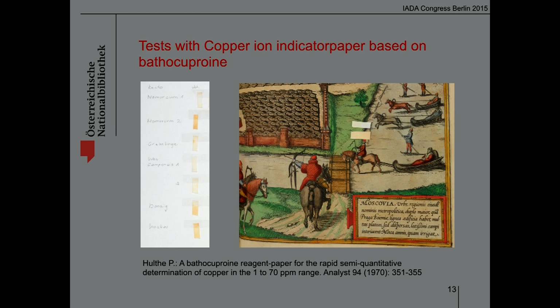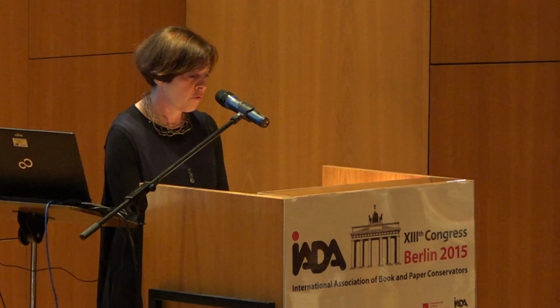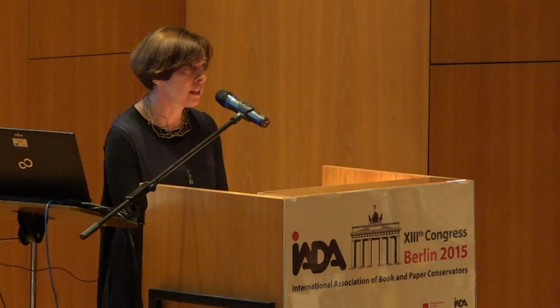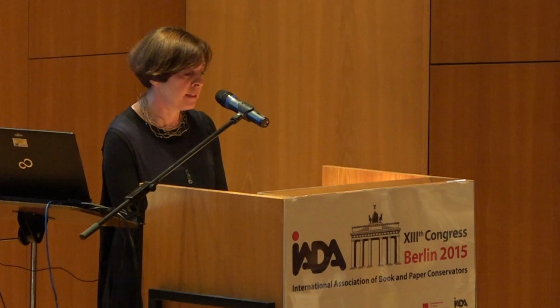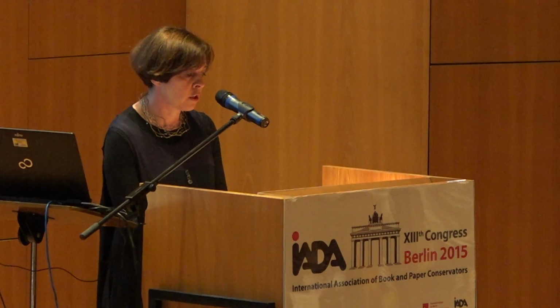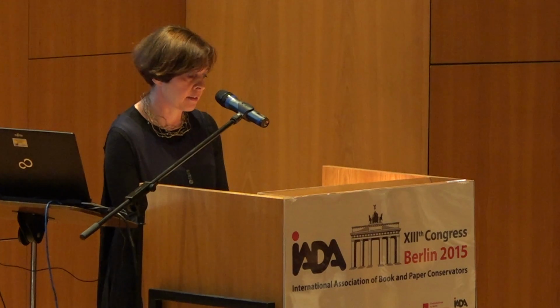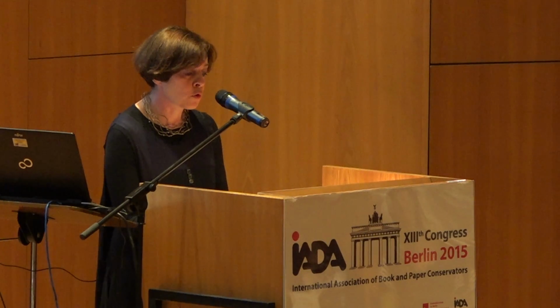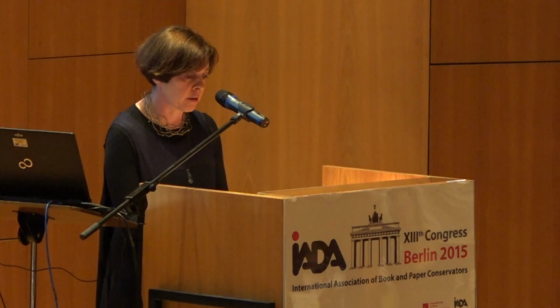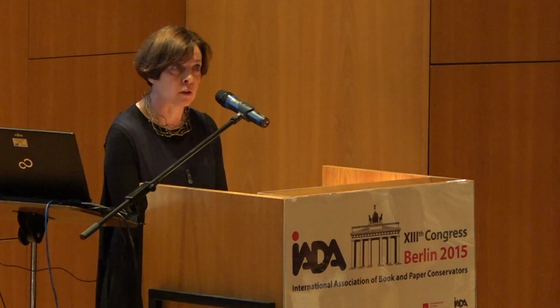We had intense discussions about chemical stabilization in the conservation of the two objects. The pros and cons of the application of BTA were considered. Finally, we decided to locally apply a 3% BTA solution in ethanol to verdigris that showed brown discoloration on the verso in both case studies. We wanted to stabilize strongly degraded areas and prevent further deterioration of pages in still better condition.